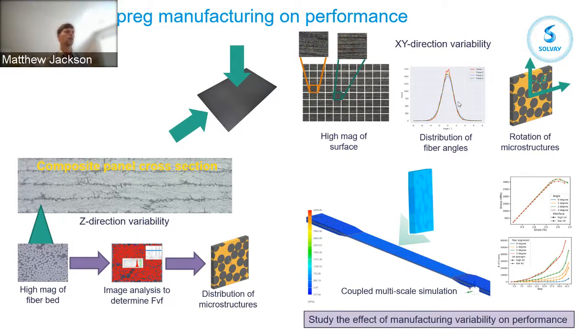Here, what I'm showing is a concurrent multi-scale simulation, or FE2 type simulation, where we develop a distribution of these different microstructures, and then we can systematically vary them to understand the performance that they have on the composite themselves. Here, what we're seeing is basically a simulated tensile coupon with different microstructures. And we can see, by varying the angle that is inherent to the manufacturing process, we do see a hit in both the stiffness and the strength.